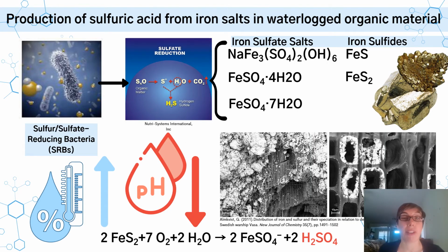Acid-base reactions can also affect organic material. It's not all a metals game; artifacts that have come from underwater environments, especially wood, are affected too. One of the cooler ways that this can happen is due to the presence of sulfate-reducing bacteria, which live in spaces where there is little to no oxygen, and as such, they rely on sulfur products like sulfate to breathe instead of oxygen. One of the byproducts of this metabolic process is the production of hydrogen sulfide, which in the presence of metal ions is reduced to form both metal sulfides, much like pyrite, which is what you see right here, as well as various species of soluble metal sulfate ions like iron sulfates, such as rozenite.